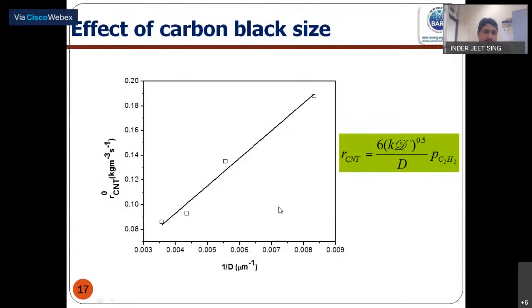If we plot the formation of the carbon nanotube with respect to the change in the diameter of the carbon black size, we get a straight line, and from there we can have a formula which determines how diffusion affects. So this is the diffusion control regime.